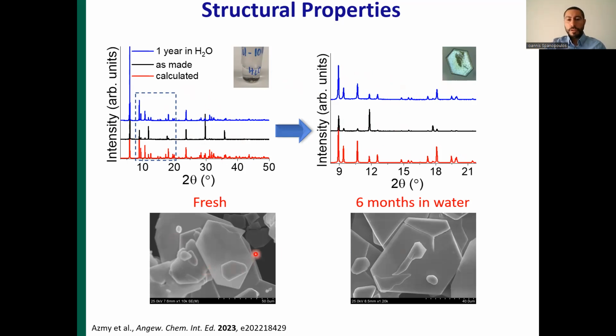On the bottom, we recorded the SEM images of the crystals. On the left are the fresh crystals, and on the right are the crystals after 6 months in liquid water. The surface of the crystals is intact. Crystals are pristine, and there are no signs of even surface degradation that cannot be recorded with the powder x-ray diffraction studies.